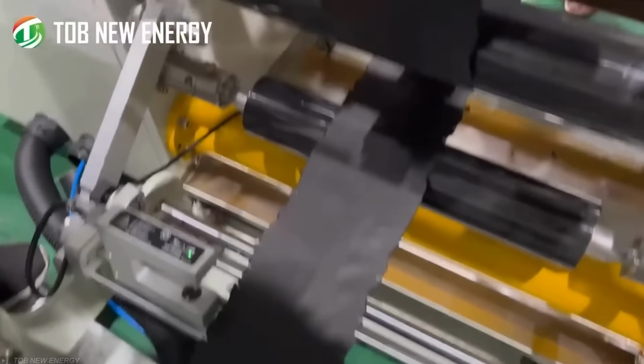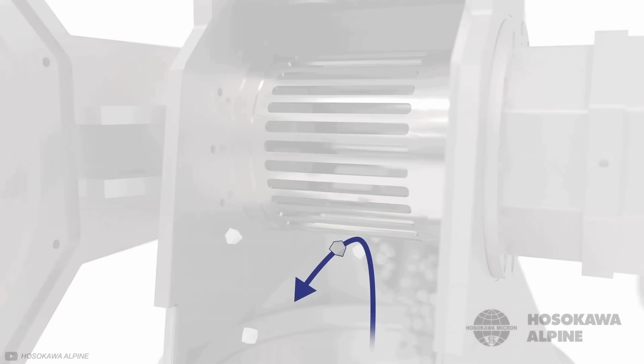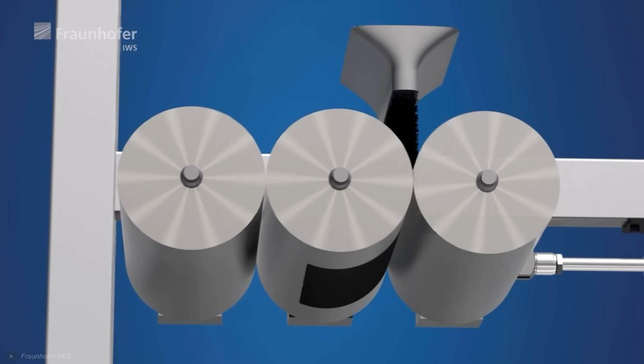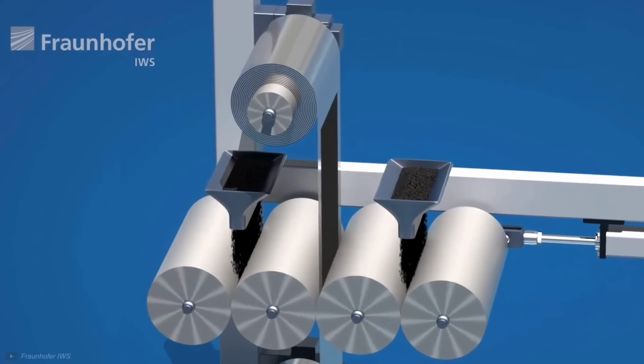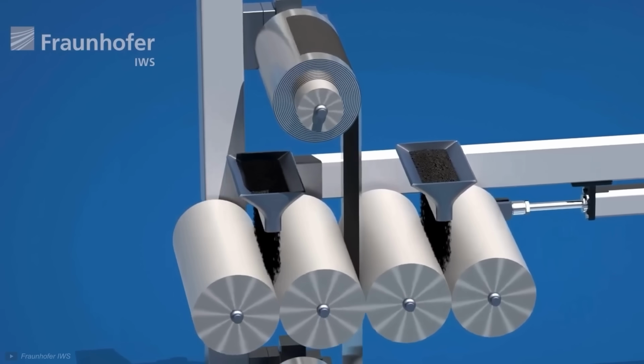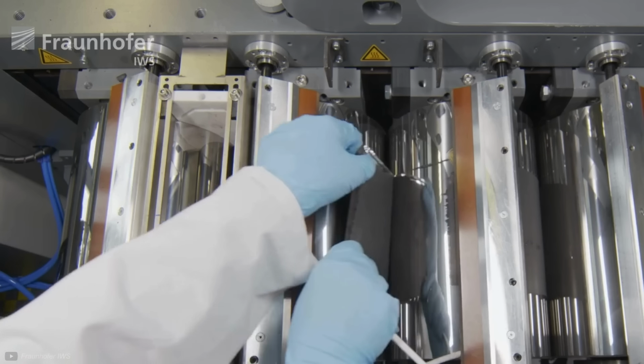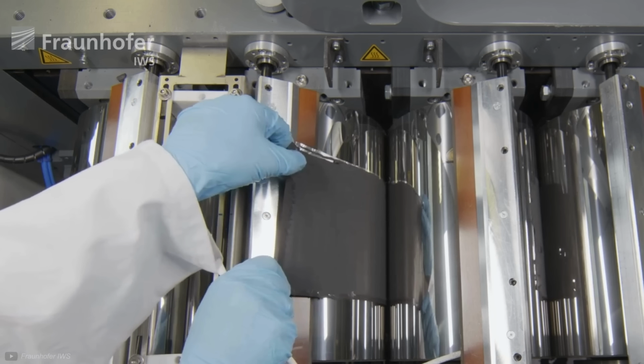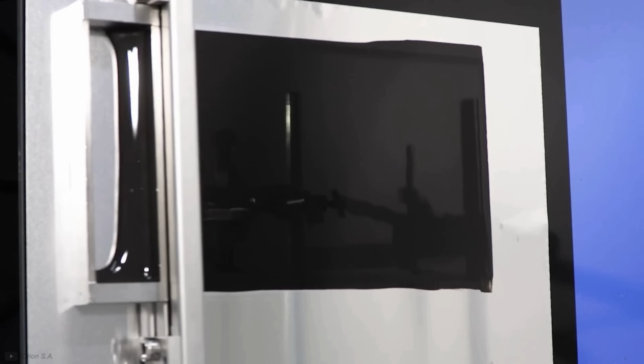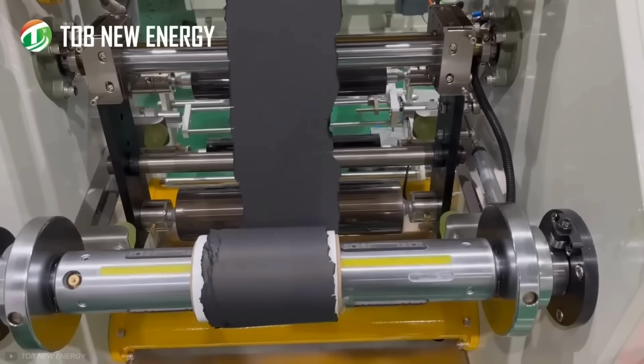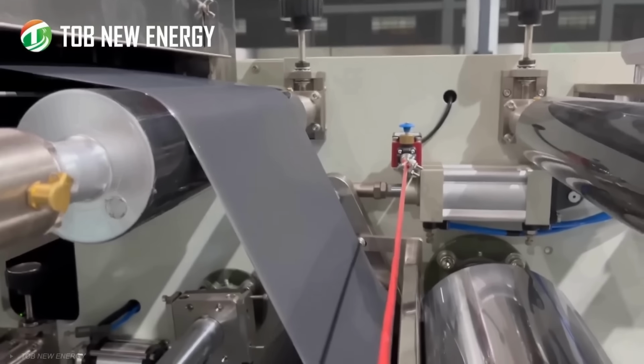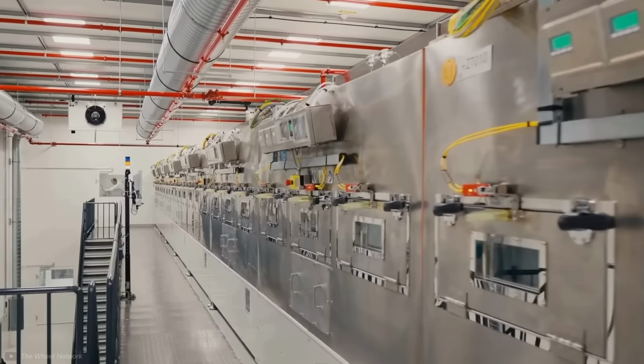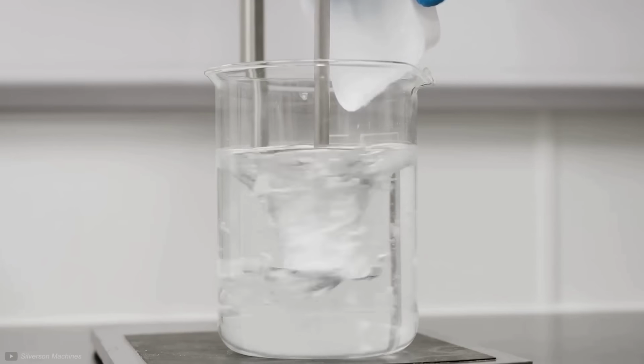drop of liquid involved. Fraunhofer, a German research institute, are also working on dry electrodes, but they do something slightly different. Instead of using a jet mill to stretch out the particles and make fibers, they use two rollers spinning at different speeds. In both cases, the resulting dry film is then pressed onto the current collectors, where the pressure and heat cause it to bond and become more dense. And because there's no liquid to make things slippery and spread everywhere, the film stays put and sticks, rather than squishing outwards like a wet slurry would. All of this means no ovens, no solvents, and no waiting around.